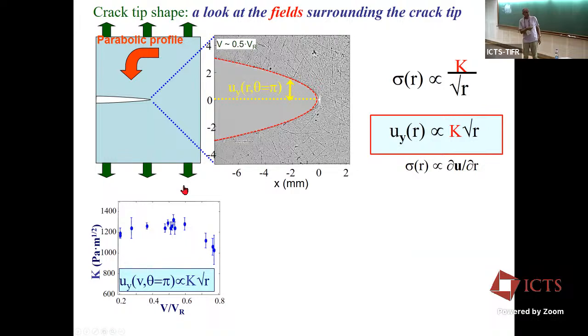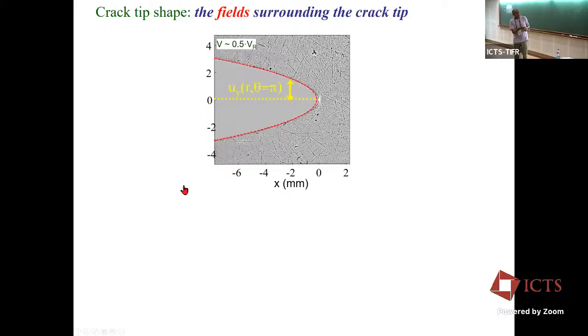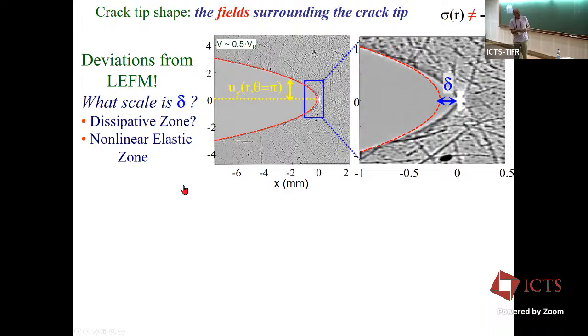We described this, and this K is not a free parameter. It can be derived from the fracture energy, which we've measured. So no free parameters, everybody's happy. But then we got greedy, as physicists tend to be. So we decided let's look closer. And what we find if we look closer is that if we expand this, there's a region where the parabola doesn't quite fit. Okay, who cares? It turns out that there's some scale here, the distance from the apex of this parabola to the apex of the real crack, empirically defined, where the solution doesn't work.